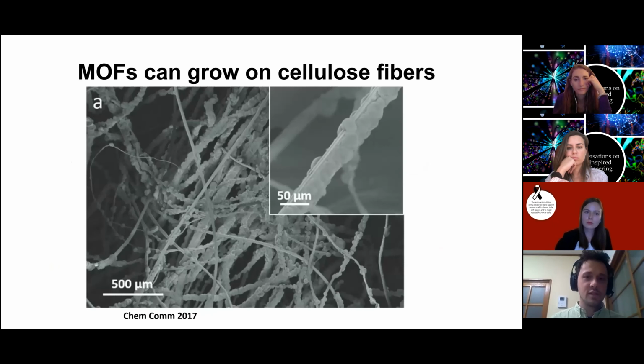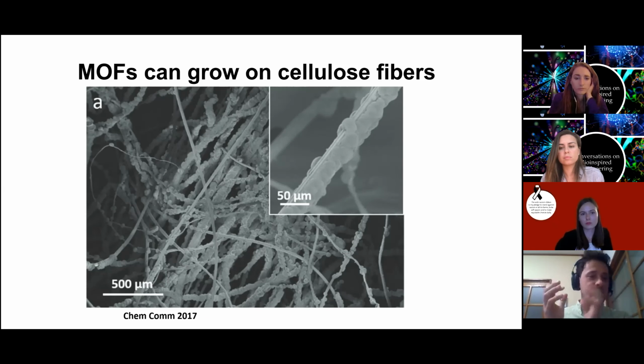Cellulose fibrils, so we just use bamboo, so increasing in complexity here. We form these, and as you can see, they're not really crystalline at this stage because the radius of curvature now is in a very awkward stage for these crystals to form. So they're amorphous materials at this point, and these fibrils essentially cause the particles, these seeds, to agglomerate and grow along the fibril. As you can also see from that, it's not fully contained.